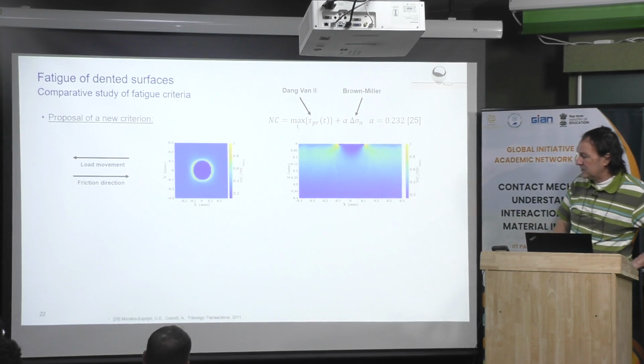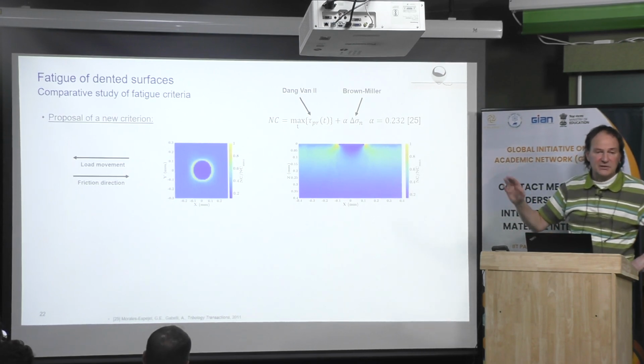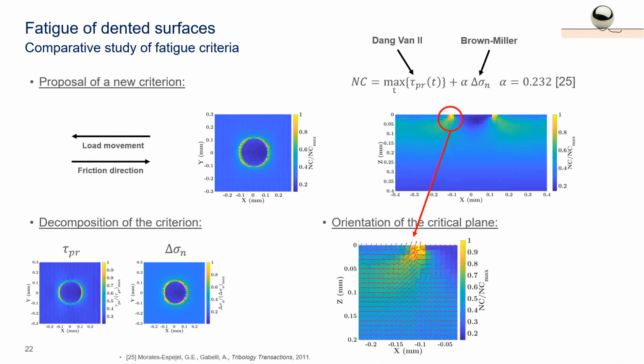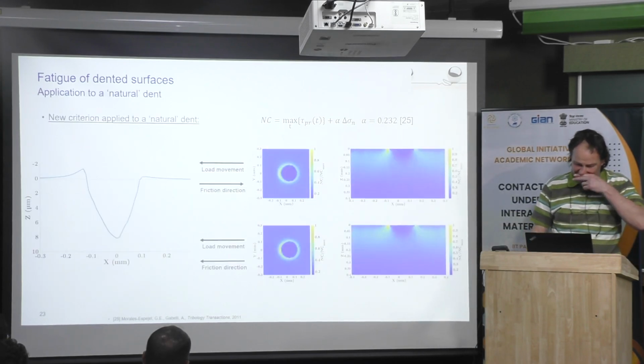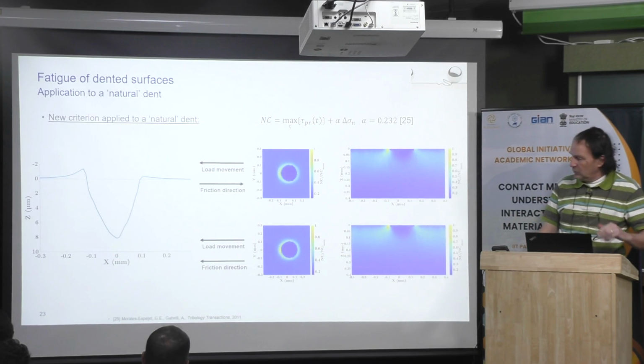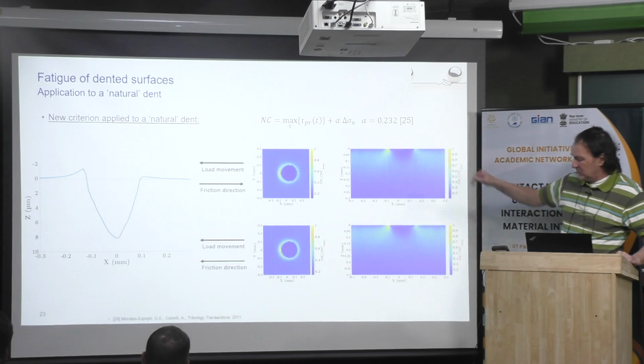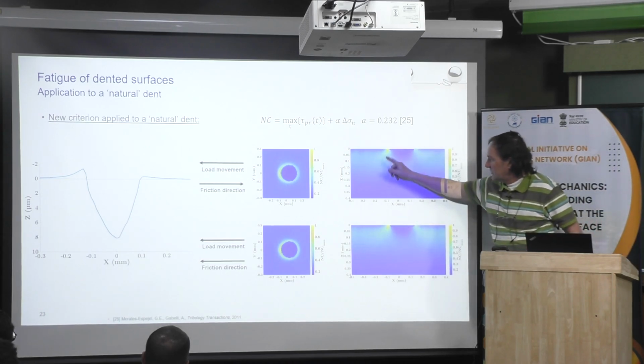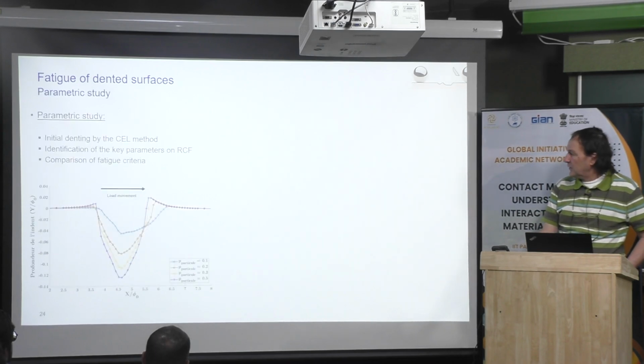Guillermo Morales is working typically on the same type of material, bearing steel, and it is also interesting for that because we don't know the parameter. Again, you can find the effect of each contribution, shear and mean stress, or here the amplitude of the maximum principal stress, and also we can find the direction of cracking. And when we do the simulation on a real dent, this is what you can find. Then we find the correct location for crack initiation.